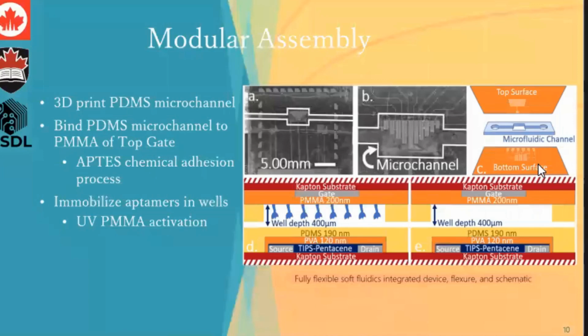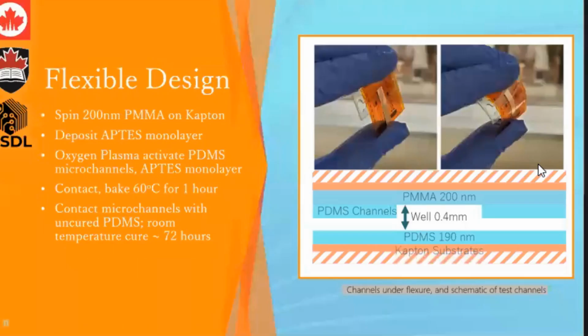And the immobilization of aptamer is a one-step process. So it's a chemical modification of PMMA, which is a thin layer that we UV activate, and then we just expose it to aptamer solution in deionized water, and we incubate for about 10 minutes. So as the previous presenter said, incubation is a critical step, and aptamers being small molecules, as long as the surface is not heavily charged and clean, the interaction is pretty good, and we get stable assemblies, which is good for months if stored in a refrigerator, and close to a month at room temperature. So that's where we are.